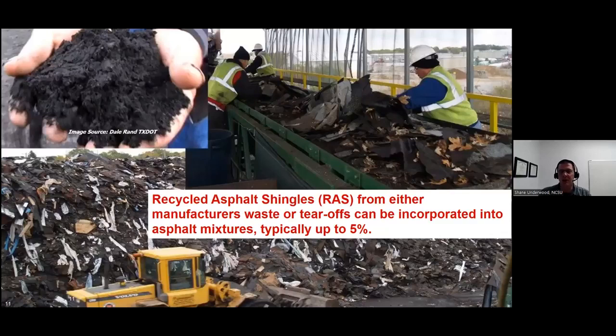As you can see in the images on the screen, there are issues that have to be dealt with, especially when we use tear-off or post-consumer waste materials. You can see these gentlemen in the upper corner here are dealing with leaves, backing paper, lots of different components in this waste stream, as you would imagine from a construction site. You can also see this in the image on the left, where you see all of the paper and all of the waste materials that come with roofing replacements. And so those materials have to be separated in order to produce very good, usable, recycled asphalt shingles for use in pavement. You can see at the top what a typical processed shingle would look like. It's very, very fine. The challenge with this is making sure that this stays dry because it can absorb quite a bit of water.